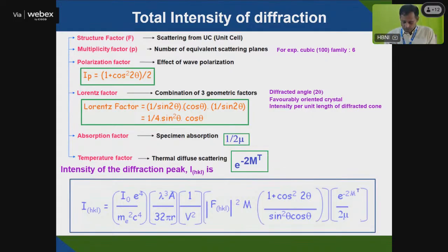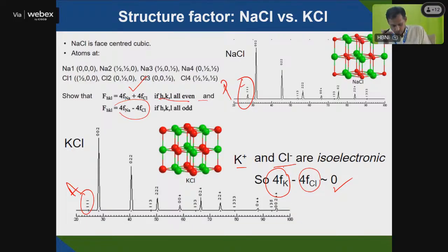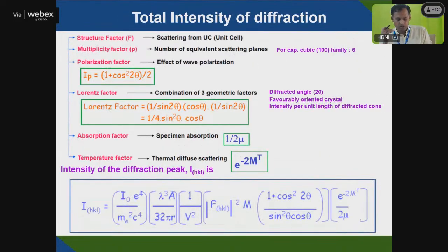So from the structure factor, you can now say whether the isoelectronic effect is there or not. That information you can get. Now, for the total intensity, I discussed only one factor, the structure factor. In addition, there is the multiplicity factor, meaning many families of planes, like the 1, 0, 0 planes, and similarly 0, 1, 0, 0, 0, 1, minus 1, 0, 0, 0, minus 1, 0, and 0, 0, minus 1. So the family of 1, 0, 0 has multiplicity 6, and that comes into the picture.